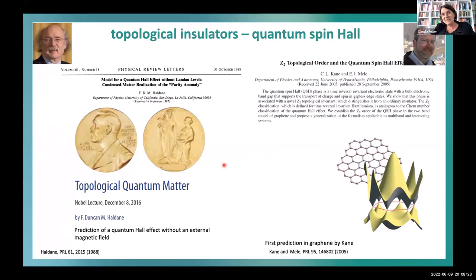And this is where we are. We are here in the magnetic spintronic community. So this is something essential, but we really still have to look for a material which has maybe the quantum anomalous Hall effect at room temperature. Because as you know, people in spintronics, they are not like the low temperature physics people, they want to have everything at room temperature. And the second big step was with the prediction of Kane and Mele that there's also the quantum spin Hall effect. So for example, in graphene.